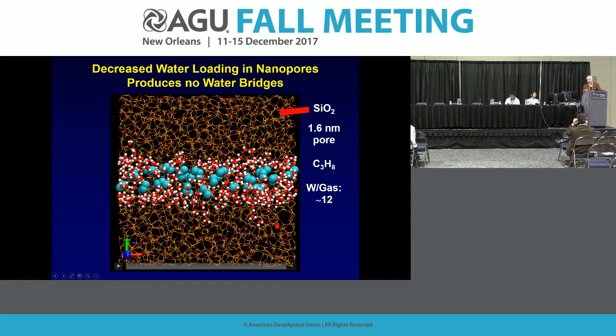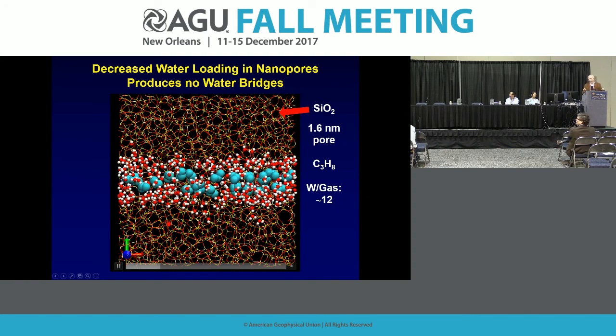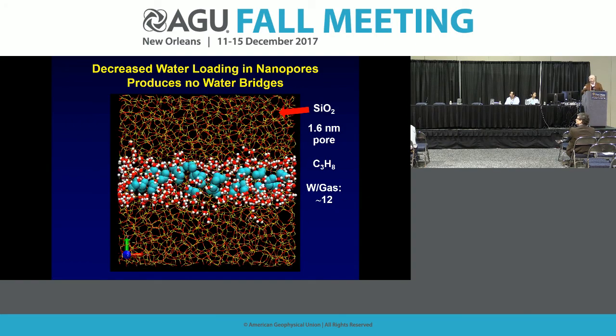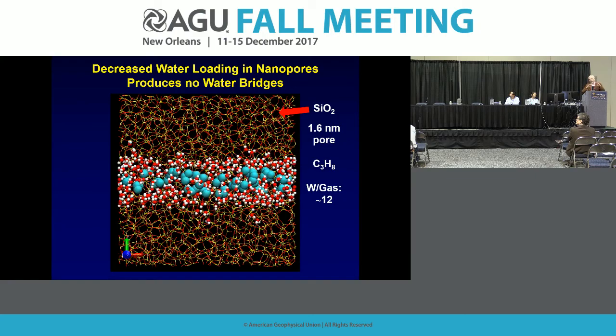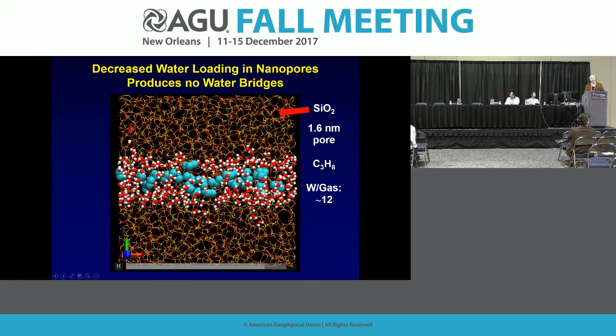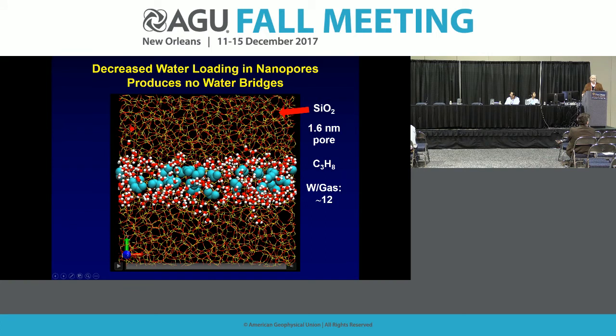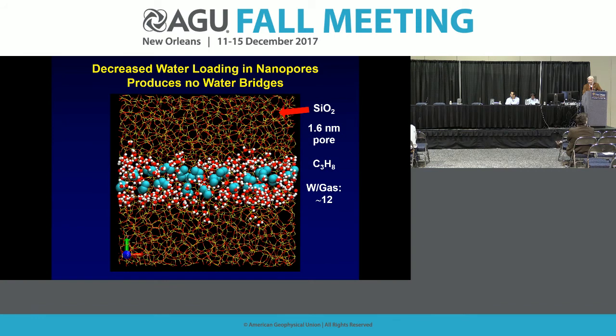Where we have a little bit lower water to gas ratio, even a 30-40% change, we see a much different kind of behavior. The methane, in this case propane, are these blue balls moving through this water. Silica is this matrix, and so now we have somewhat enhanced transport, enhanced solubility, if you will, because there's more space for that methane to occupy in that pore. So again, a very interesting outcome that we've been able to predict from MD.